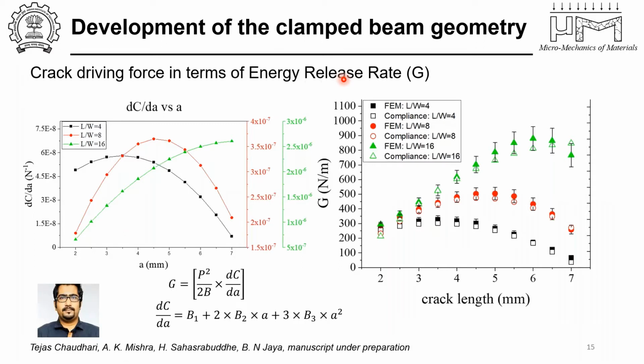But we also wanted to look at the ability to measure energy release rate using the same particular geometry, because many people tend to report fracture toughness values in terms of the critical energy release rate, GC. So for that, we wanted to evaluate how that changes as a function of crack length. We evaluated the compliance change as a function of crack length, and we fitted it into this particular equation. And we get the G as a function of crack length as well. And we have given solutions for the same set of beam aspect ratios again. And it matches very well what we get directly from FEM and what we get from the compliance technique. So that shows us that we are heading in the right direction.